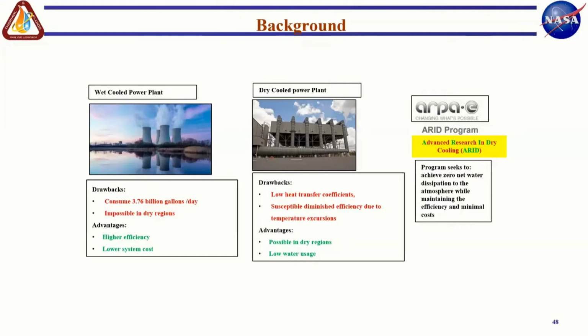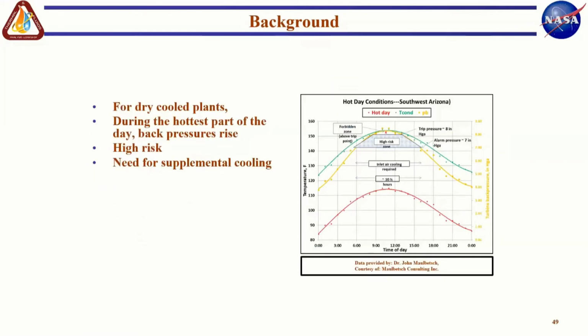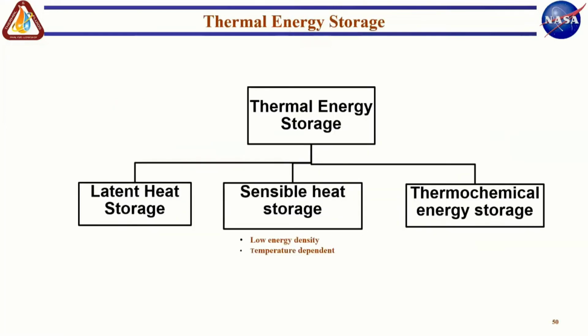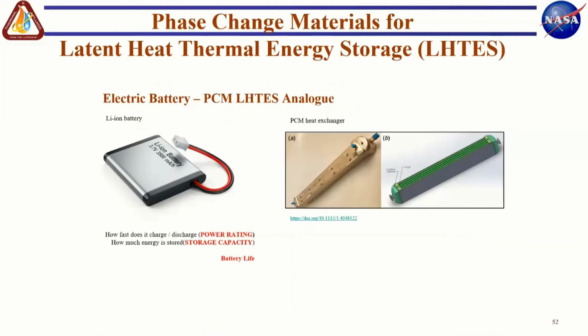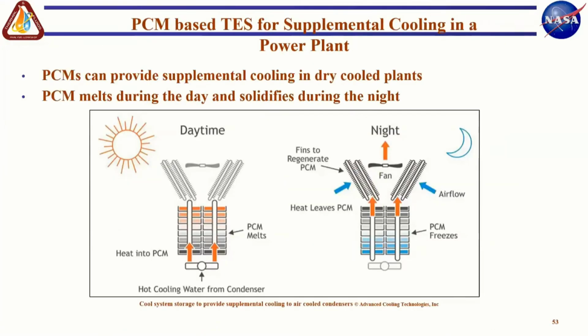So we were fortunate enough to be funded by the ARID program from ARPA-E. And the idea there was to use dry-cooled power plants. I'll skip this graph. So the idea there was to use phase change materials for cooling either the steam directly, which is the configuration shown on the left, by melting PCM instead of using the ambient air. The other configuration is to cool down the ambient air by passing it through a bank of PCMs. While the PCM melts, it generates the cold air that then cools down the steam. And then the idea was you flow the cold air at night, the desert air, and you freeze the PCM back during the night, and you melt it during the day.